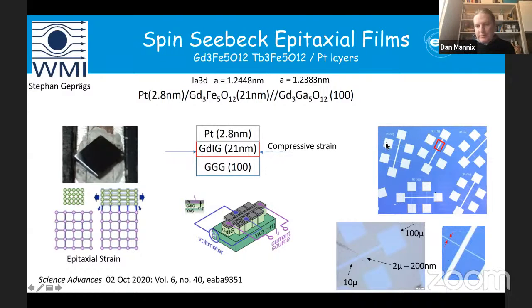These are the pads which are used to connect electrodes to measure the currents generated and apply the currents to the materials. And these have typical sizes. They're about 100 microns for the pads, and they come down to these wires, which are on the order of micron size. In fact, with these lithography methods now, you can make wires from about 2 microns all the way down to 200 nanometers by using different kinds of lithography methods. So all of these materials are very high quality indeed and state of the art, and that's what we come in with our X-rays to study.